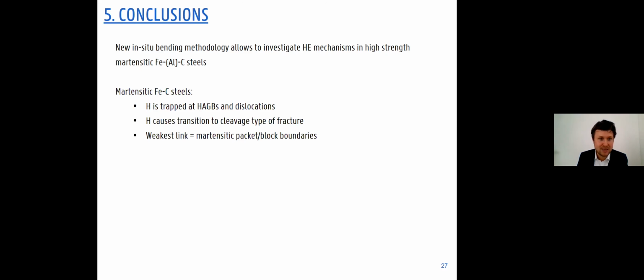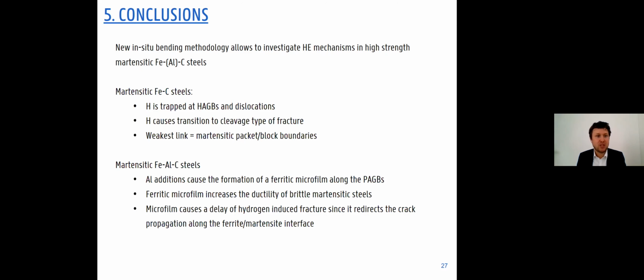Why? Because the weakest link is the martensitic packet and block boundaries that were able to trap a lot of hydrogen, as proven by the TDS. When we then add aluminium, well, this aluminium addition causes the formation of a ferritic microfilm along the prior austenitic grain boundaries. So we have this very fine microfilm of ferrite that can act as a glue. And this ferritic microfilm increases the ductility of the brittle martensitic steels. This was then proven by the ECCI, EBSD, and nanoindentation tests. And next to that, the microfilm also causes a delay of the hydrogen-induced fracture since it redirects the crack propagation along the ferrite-martensite interface.